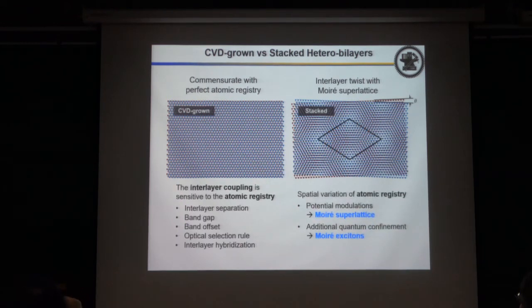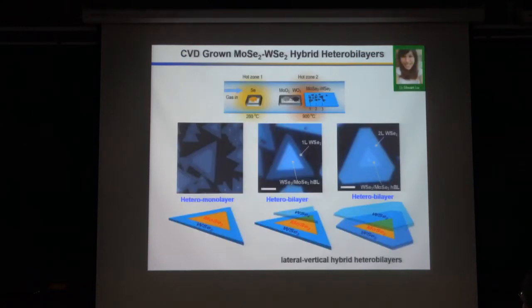And when you have a Moiré pattern, like a Moiré superlattice, you will have spatial variation of atomic registry. So this atomic registry will also have some spatial modulation in the band gap. So you will have potential modulation for the electron or hole or for exciton. So you artificially create a superlattice for electron, hole or exciton in this case.